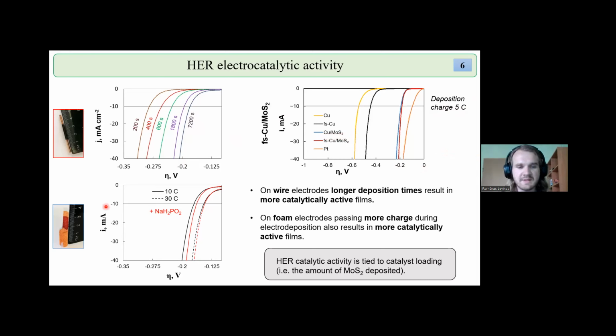And on copper foams, again, the same trend of charge is continued. So more charge has been passed and more material deposited on the copper foam electrodes. And again, we see that these electrodes reach even higher current densities at lower overpotentials. So the overall conclusion is not surprising: the hydrogen evolution reaction activity is tied to the amount of catalyst that is deposited.